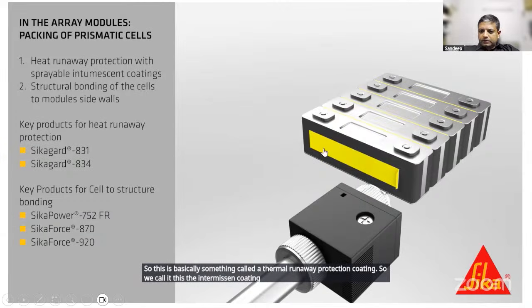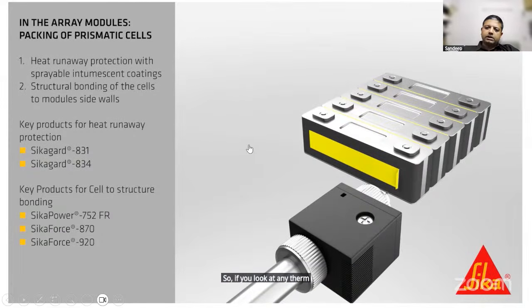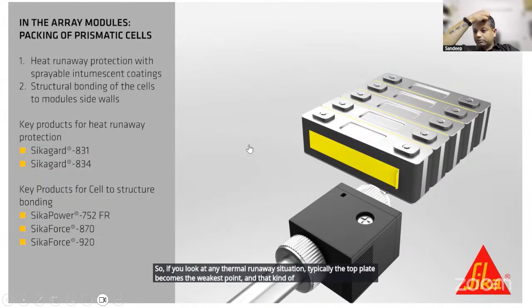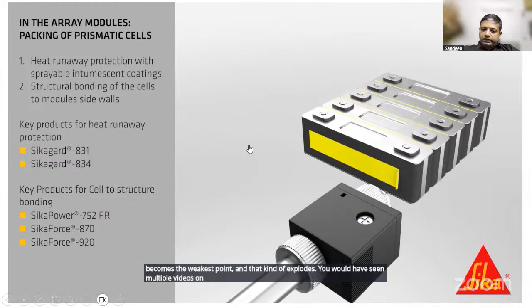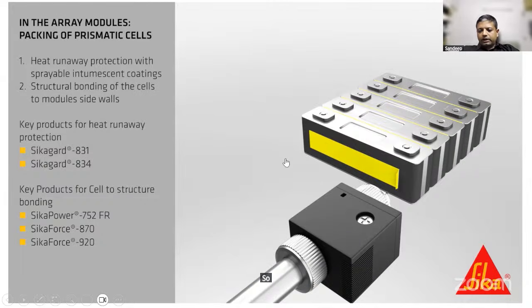These are applied not generally between the cells, but I would say 99% of the current OEMs apply it underneath the top plate, the battery top plate. If you look at any thermal runaway situation, typically the top plate becomes the weakest point and that kind of explodes. You'd have seen multiple videos on this. And the reason for that is aluminum casing typically gives away at about 650 to 700 degrees Celsius. So this coating is called an intumescent coating.